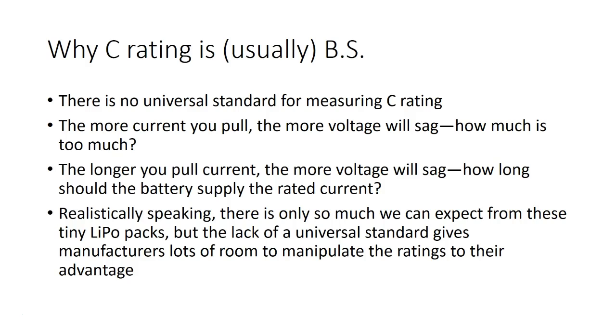The reason C rating is usually BS is that there's no universal standard for measuring it, so manufacturers are free to say whatever they want — especially if one manufacturer is selling a 65C 1300 milliamp hour pack and somebody else can find a way to label it 75C, suddenly people are going to buy that battery. What I would ask you to take from this video: milliamp hour ratings can be abused but in my experience are usually not too far off. C rating — just ignore it. Assume that most LiPos today are going to give you around 45C at best, and you can't get that information from the sticker on the side of the pack.